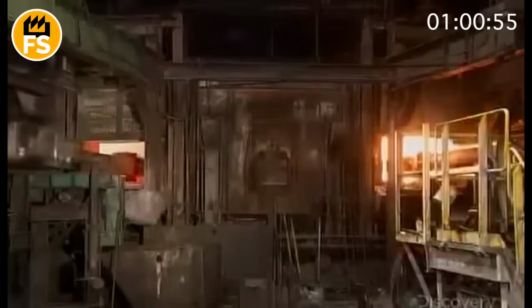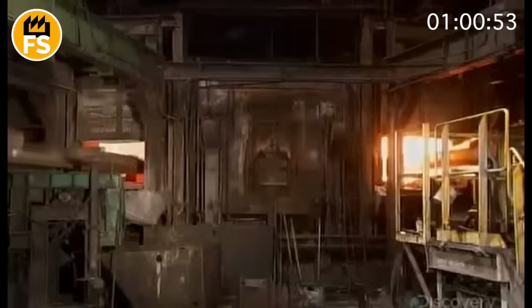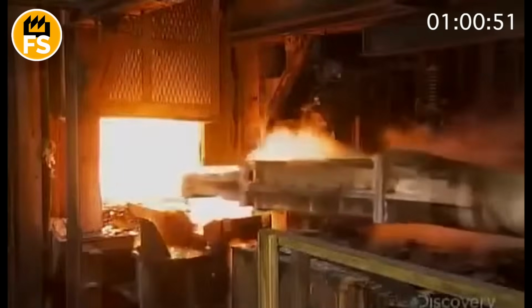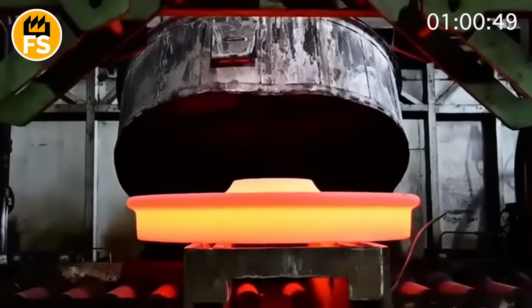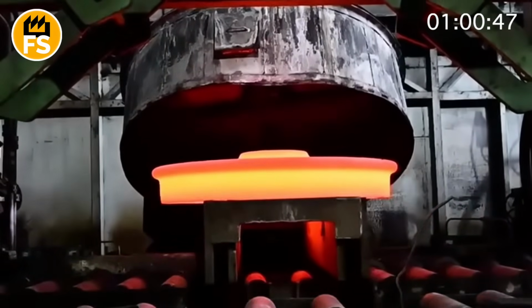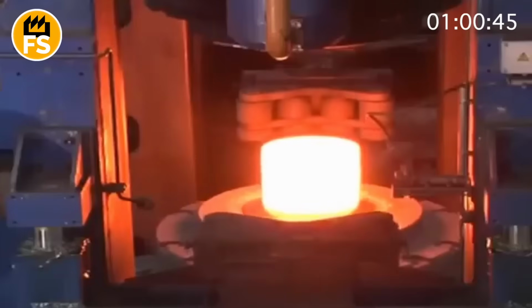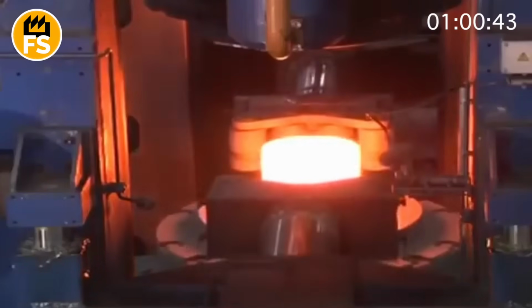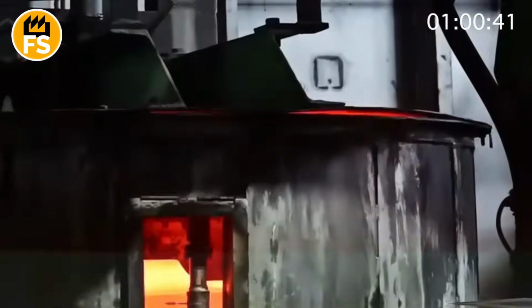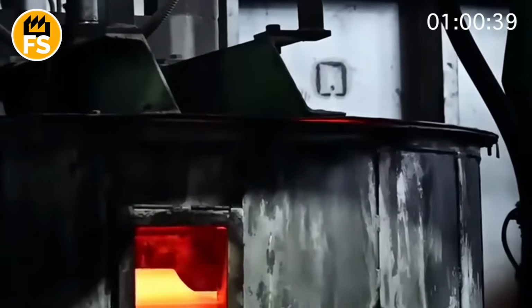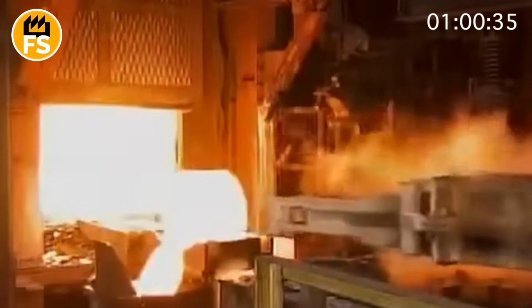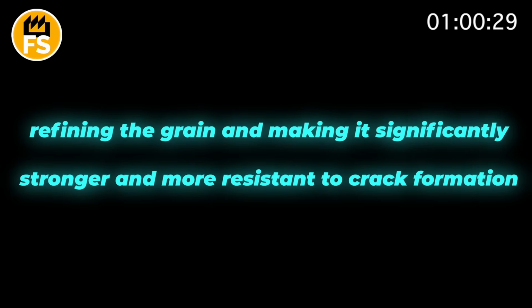After this, the red-hot blank, already resembling a wheel, is immediately transferred to a rolling mill. Here it is clamped between several powerful rollers that, with enormous pressure, roll and form the precise profile of the rim and flange. This process not only gives the wheel its final shape, but also works the metal's structure, refining the grain and making it significantly stronger and more resistant to crack formation.